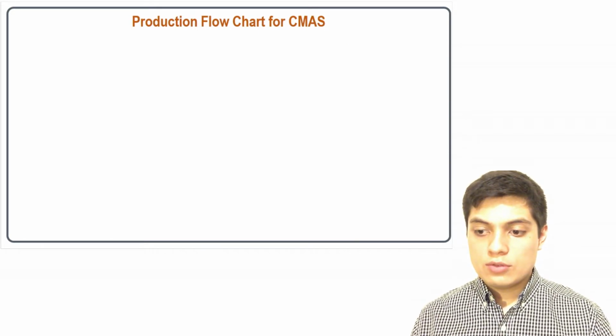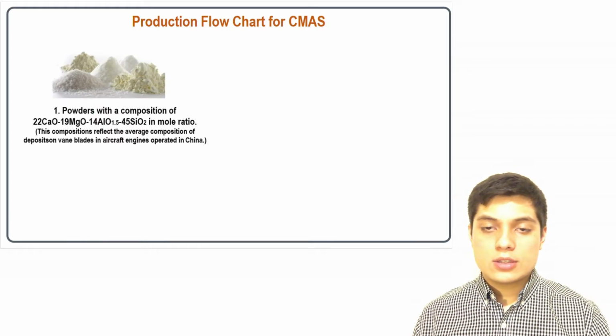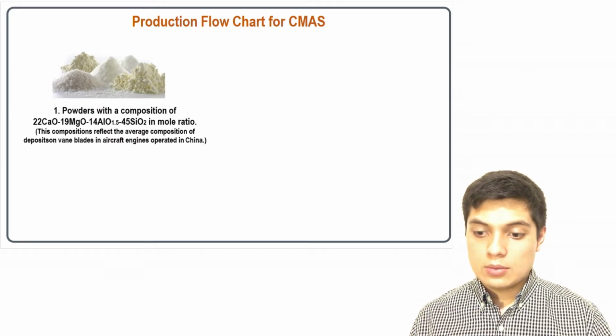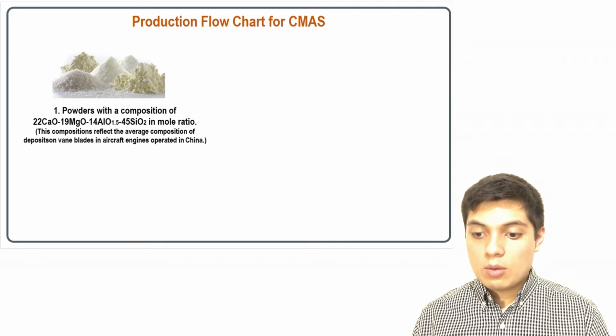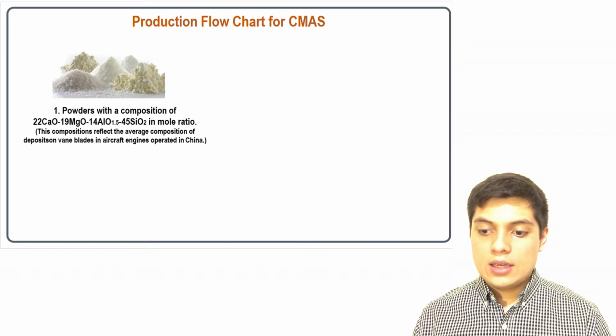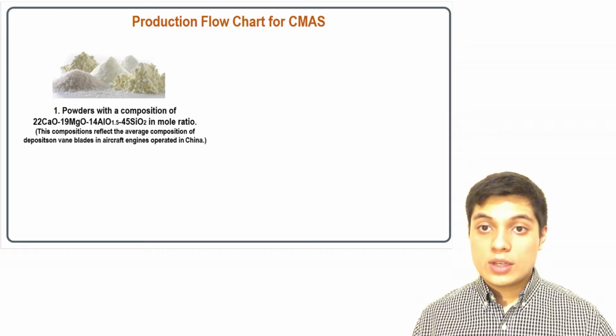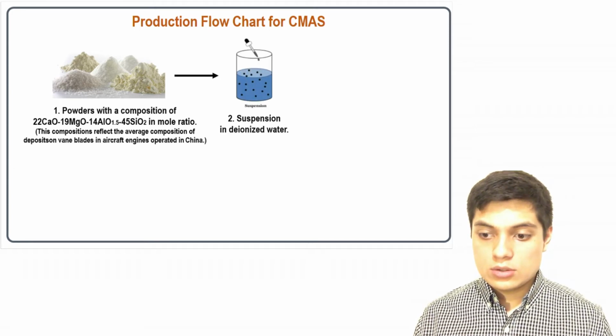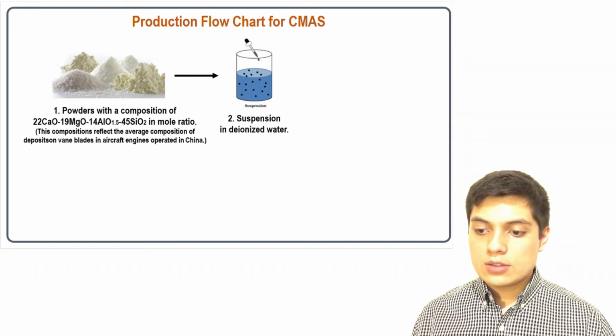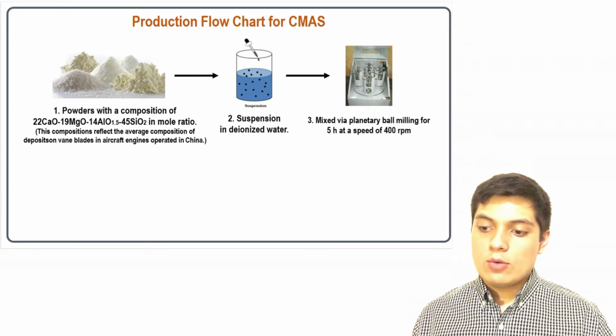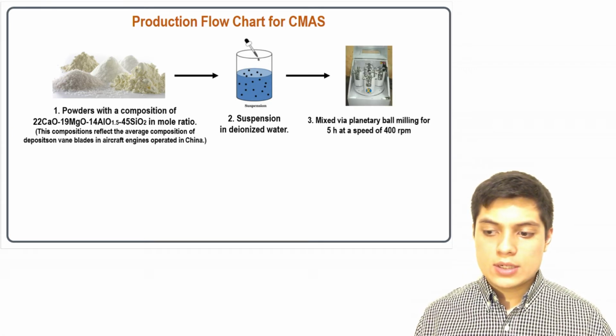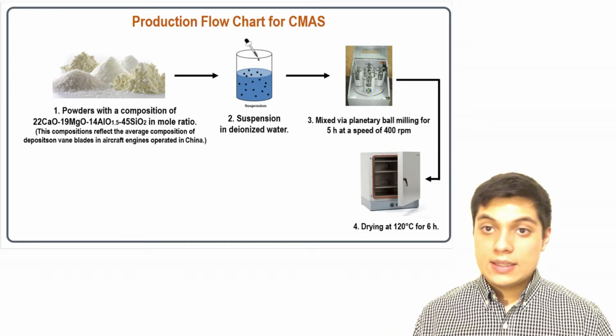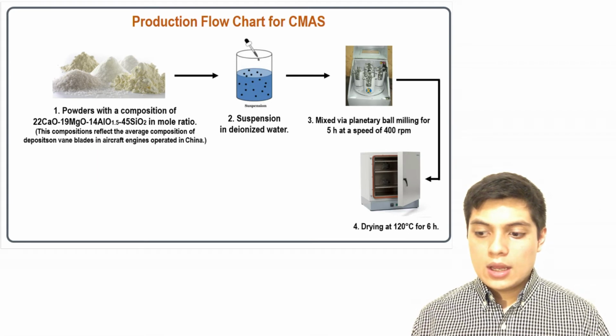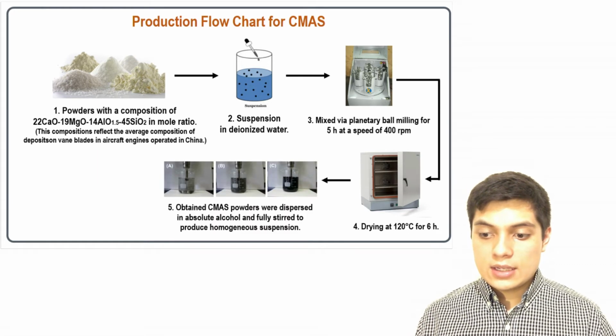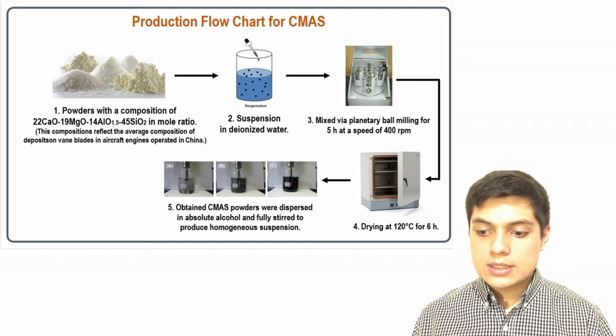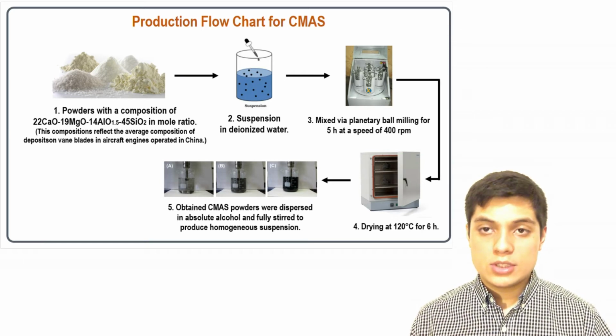And then we have the production flowchart of the CMAS, and the powders with this composition that we can observe are the average composition of the deposits on turbine blades in aircraft engines in China. So as we can see, it is a very important average composition. Then the CMAS were suspended in deionized water. Then they were mixed via planetary ball milling for 5 hours at 400 revolutions per minute. Then they were also dried at 120 degrees Celsius for 6 hours. Finally, the obtained CMAS powders were dispersed in absolute alcohol and fully stirred to produce a homogeneous suspension.